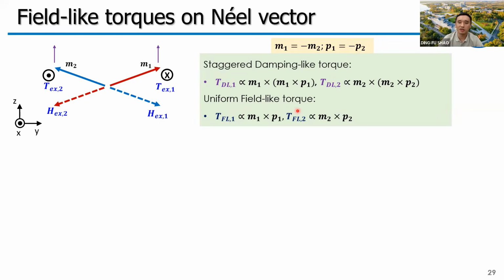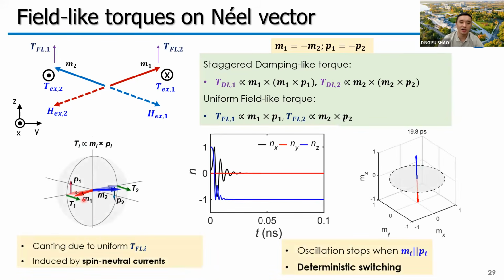But the field-like torques, M cross P, for the two sublattices are parallel to each other. This parallel field-like torque can generate a canting of the two moments, and then the exchange torque can drive the ultra-fast rotation of the Néel vector. And when the moments are rotated parallel to the spin polarization P, this field-like torque will vanish. Then the rotation will stop, and we can have the deterministic switching of the Néel vector, like I showed here.